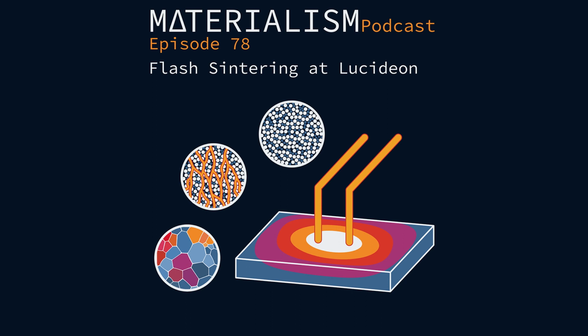So is this like arc melting? In arc melting, you've got a really big voltage difference and it actually arcs across a vacuum and that melts your sample. This is not that. You're not dealing with that high of voltages. But my impression is that with flash sintering, you're dealing with higher voltages than SPS. I mean, those can operate at like 10 volts, just really high currents. What's the typical voltage range?